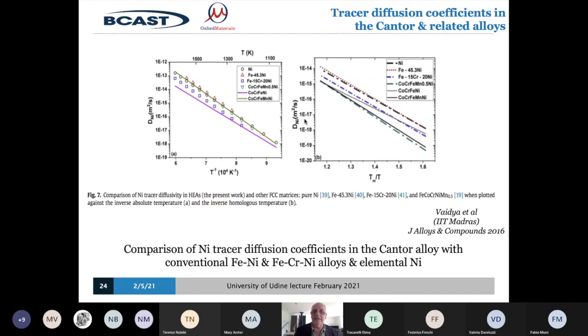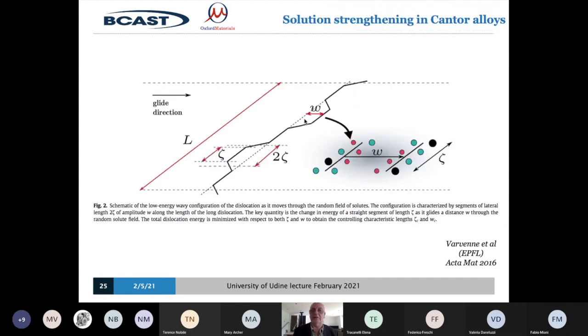Now, I've already mentioned the strength and the ductility, or the fracture resistance, which is related to the ductility, the ability for the material to deform. And this depends on things, lines like this black line here, which are called dislocations, which are a defect in the crystal. So if you have a face-centered cubic crystal, as I've shown you, there will be lines of defects. And the reason you get the deformation behavior, the reason that metals can be plastic, the reason they can resist fracture, is because under enough stress, these dislocations begin to move. But the stress isn't very high, which is why they're not very strong. And you have to try and strengthen them.